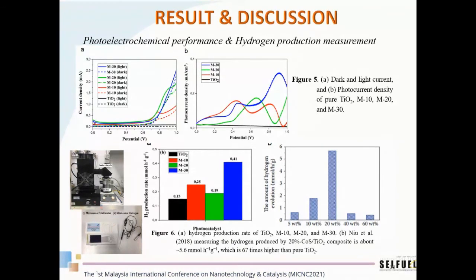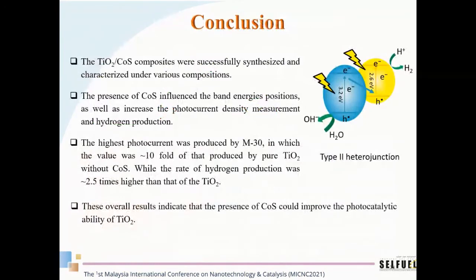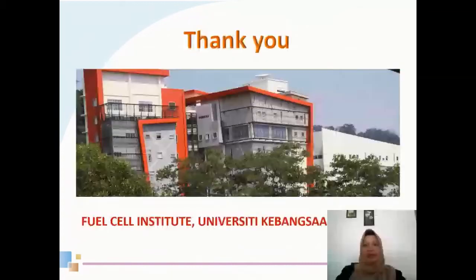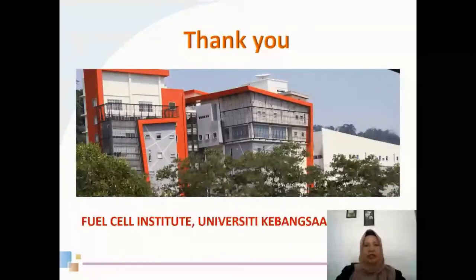Meanwhile, in our study, we only use 0.4 molar sodium sulfate solution without adding a sacrificial electron or proton source like methanol. So we can say that the hydrogen in this study was produced purely from the water splitting molecule and not from the electrolyte or other sources. For the conclusion, the overall result in the study indicates that the presence of CoS could improve the photocatalytic ability of TiO2. Okay, that's all my presentation, and thank you.